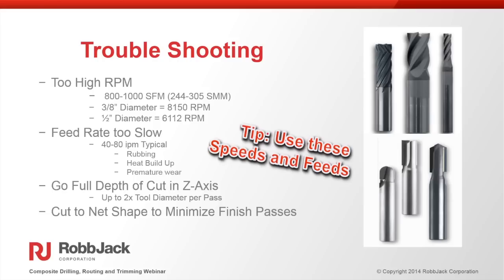On the converse side, we see a lot of times people going too slow on the feed rate. So then they're just rubbing the tool, building up heat, and you get premature wear. So to recap, using the right speeds and feeds and the right depth of cuts, you can typically go up to about 2 times the diameter in depth of cut per pass. And then if you cut the parts right to net shape, you really minimize cycle time, and you get longer tool life.